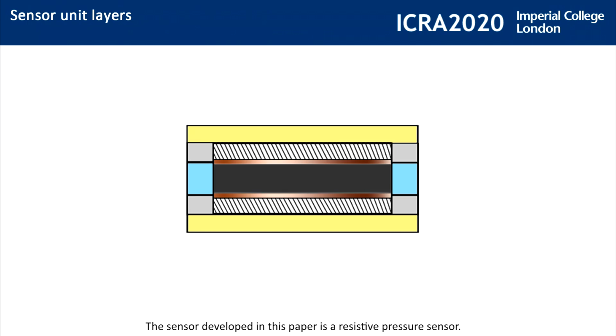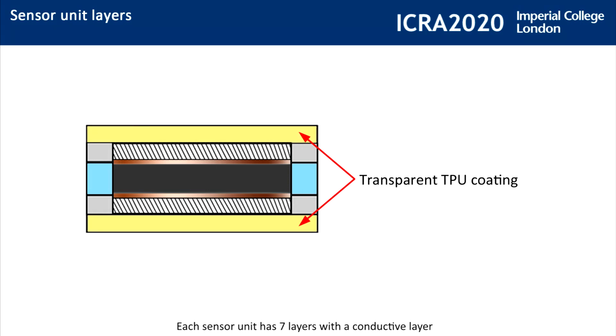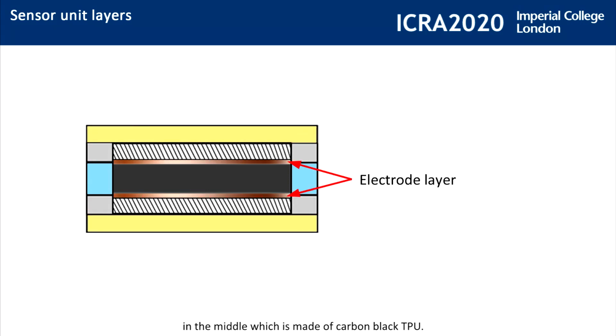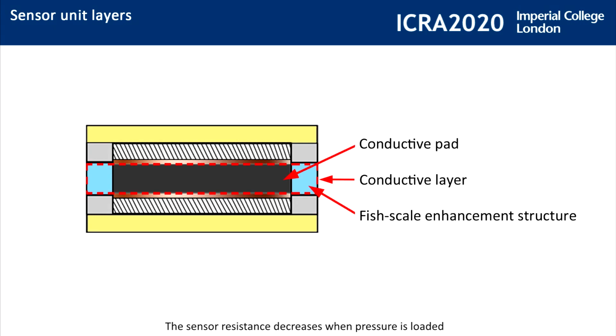The sensor developed in this paper is a resistive pressure sensor. Each sensor unit has 7 layers with a conductive layer in the middle, which is made of carbon black TPU. The sensor resistance decreases when pressure is loaded as the conductive path of this layer is shortened.